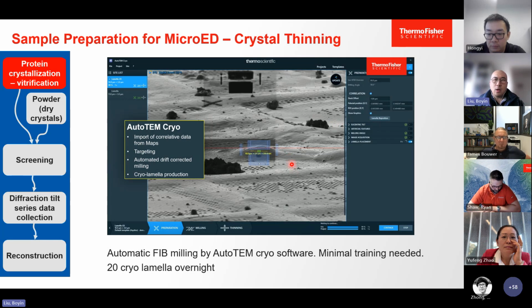And you only need minimal training, because it's different from cryotomography, where you have to spend lots of time optimizing the recipe so that you get a very thin lamella for tomography. For MicroED, you don't really care about the thickness too much. Anything between 200 to 500 nanometers is okay. So you can just use a default factory recipe, and easily get lots of MicroED lamella quickly with very minimal training.